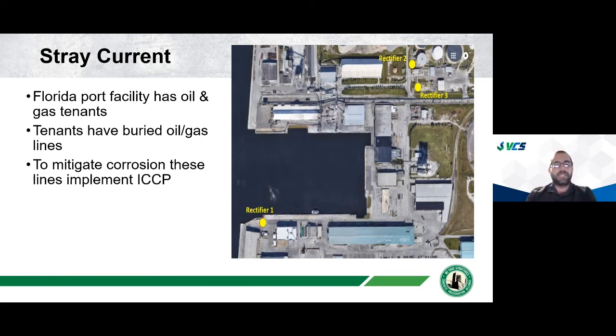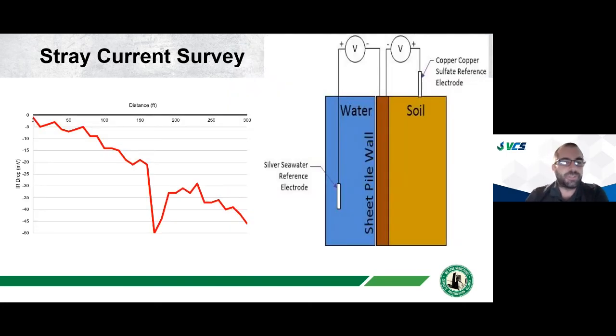And so what we did is a potential survey. Using the reference electrode, we measured the potential of the wall on the soil and water side while we turned on and off the oil and gas rectifiers. And what we noticed is, as we turned the oil and gas rectifiers on and off, the potential of the steel wall was changing significantly. And that's a sign of stray current.